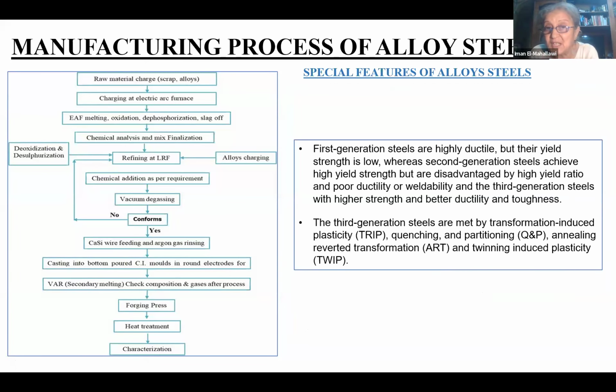This manifestation is actually obvious in the new grades of steels. The first generation of steels was highly ductile, but the strength was low. In the second generation, we could achieve high yield strength, but at the expense of ductility and toughness. The third generation steels, which are now investigated and actually in the market, like the TRIP and the TWIP, transformation-induced plasticity and twinning-induced plasticity, and quenching and partitioning. All these groups of advanced steels can achieve strength and toughness exceeding 2 times the conventional types of steels, despite the fact that they are based on the same chemical analysis.